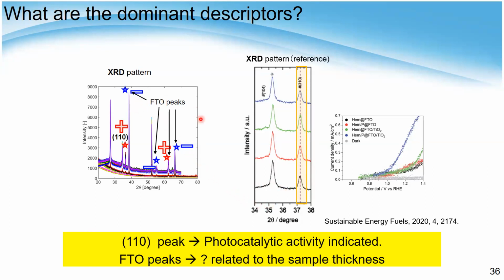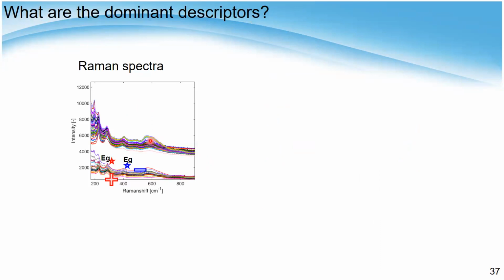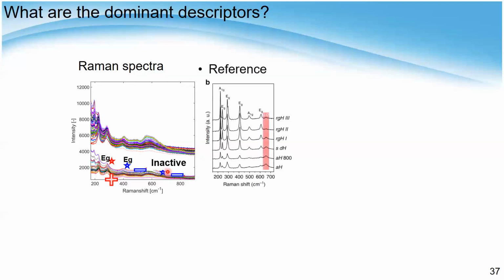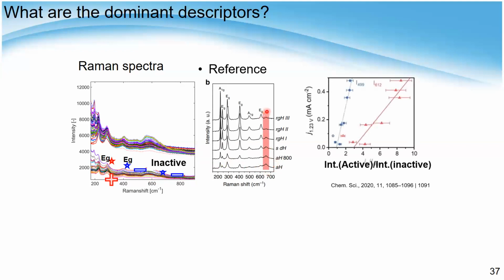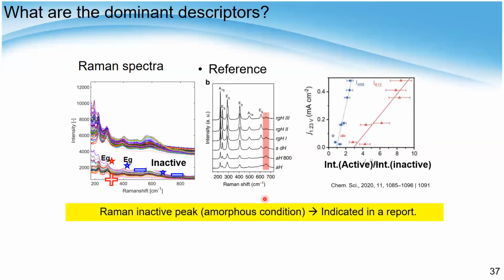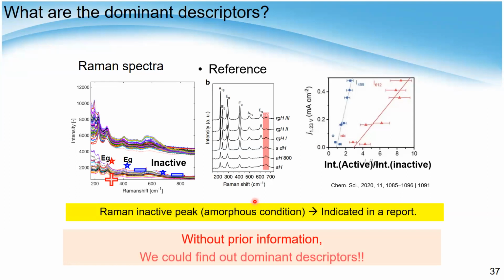There are several FTO peaks selected too, but possibly they are related to the sample thickness, though not much clear. And also in the Raman spectra, several peaks are indicated, but one of the unknown peaks, which is an inactive peak for Raman, was selected, and we didn't care for it because it looks like just a background peak. But again, this peak was also suggested by some other research indicating that this peak correlated with the activity, meaning that this is Raman inactive originally, but in the amorphous condition, it gives the peak. So again, here we didn't know much information in advance, but without prior information, we could find out several dominant descriptors in this case.